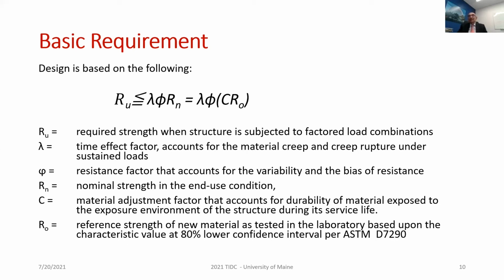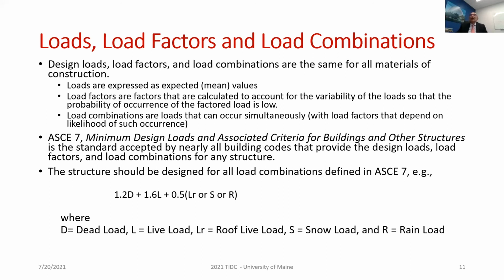If we consider the meaning of the strength in the end-use condition, we can express it as a reference strength, R sub naught, which is the strength of the new material as tested in the laboratory, and a coefficient, which is a knockdown factor, the material adjustment factor, that accounts for the exposure environment that the structure is subjected to during its service life. Let's look at each component.